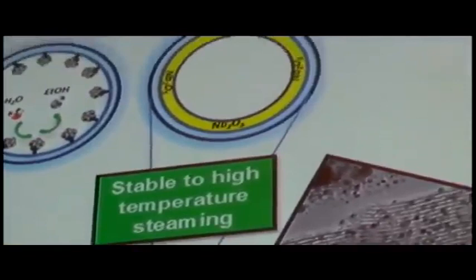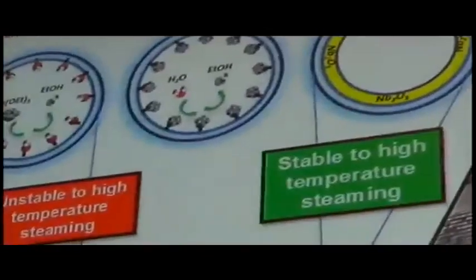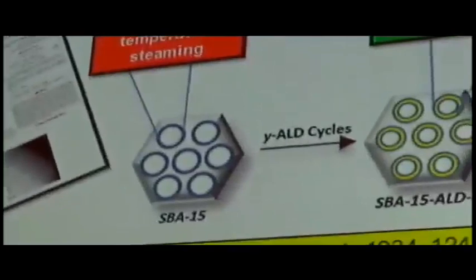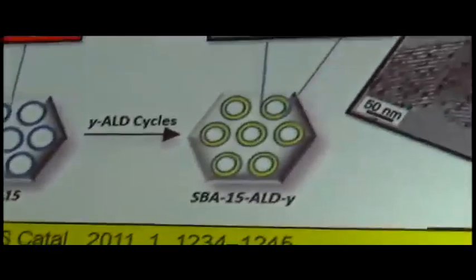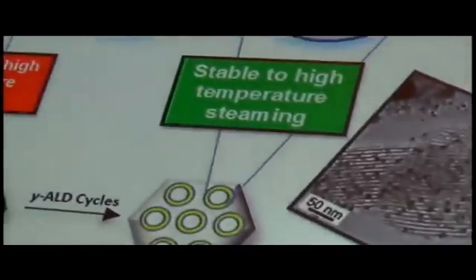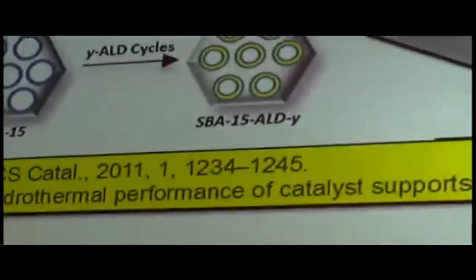One of the exciting things we've done recently is to do overcoating on very unstable types of material. What you see here is some work we did on the overcoating of the mesoporous molecular sieve, SBA-15, which has been known for a long time, but it is very unstable. You hit it with steam or liquid water, you lose most of the surface area of this material due to collapse of the pores. We found that by just putting a few layers of niobia inside of that material,